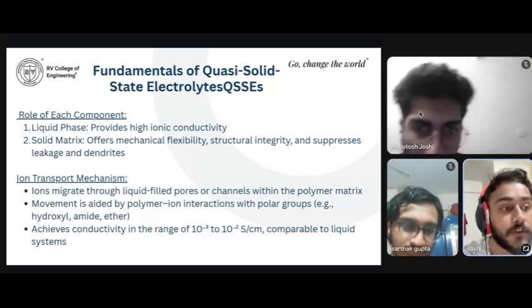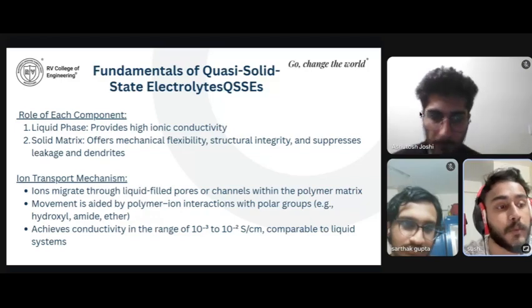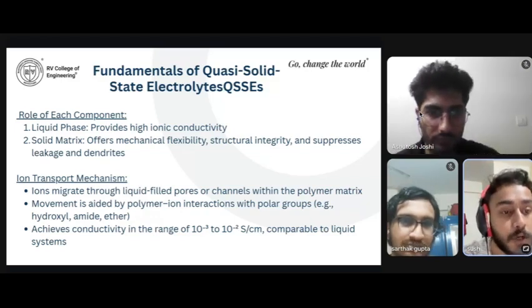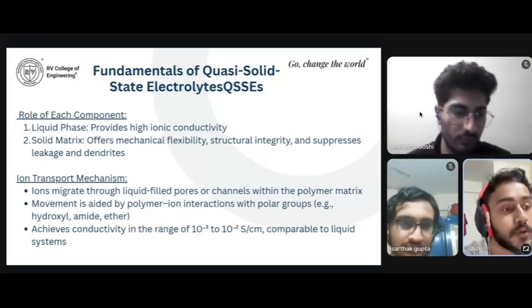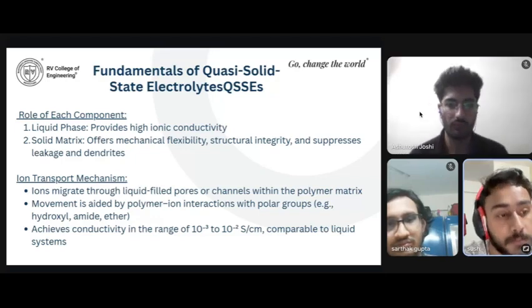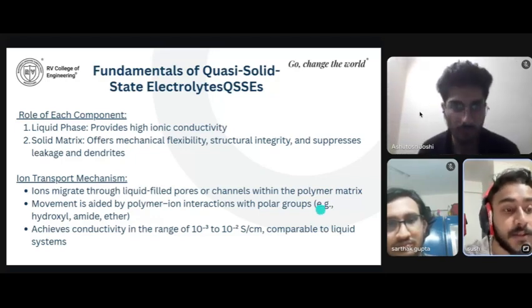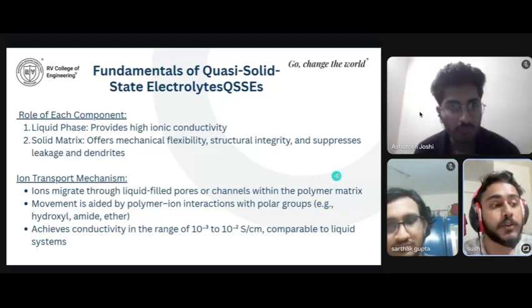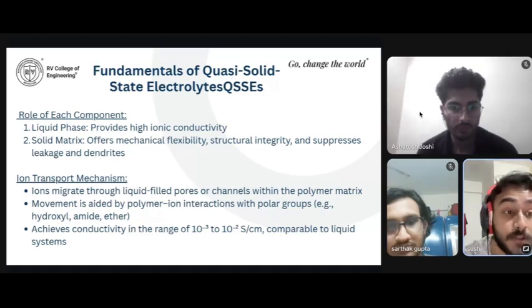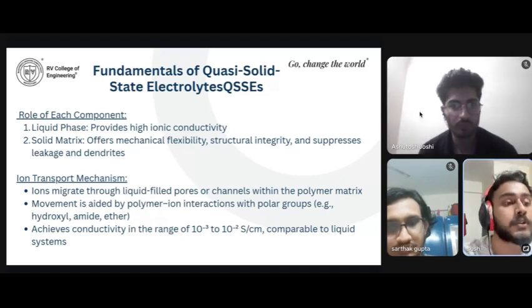Now we will talk about the ion transport mechanism. Ions move through liquid-filled pores in the polymer. Their movement is supported by polymer-ion interactions with polar groups like hydroxyl or ether. This allows for conductivity in the range of 10^-3 to 10^-2, which is almost as good as liquid electrolytes. So now, next slide.